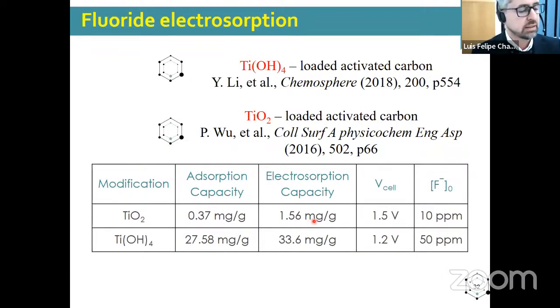Of course, as in the case of arsenic, there are several methods to remove the fluoride, like ion exchange, electrocoagulation, electrodialysis. But usually these two, especially these two, are a little bit more expensive, especially when you use, for example, membranes. No? And that's why we propose electrosorption as an alternative. And there are recent reports related to fluoride electrosorption using carbon electrodes, but modified with titanium dioxide or titanium hydroxide, in which their electric polarization promoted an increase in the removal capacity and velocity compared to the pristine carbon electrode.